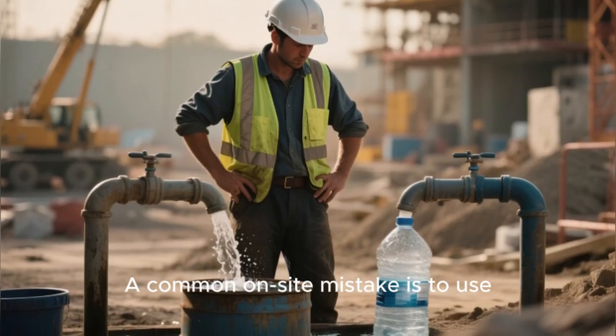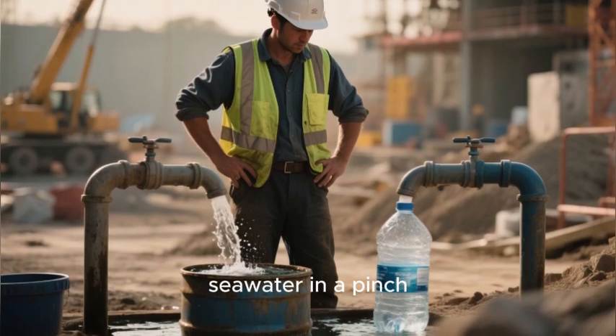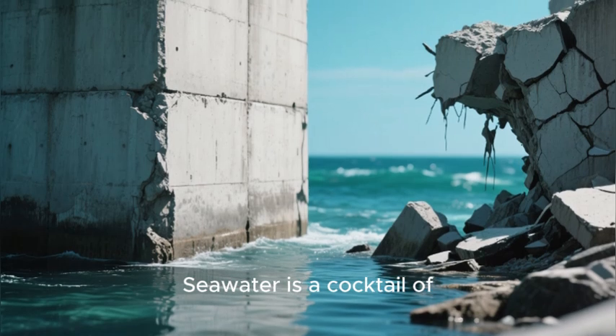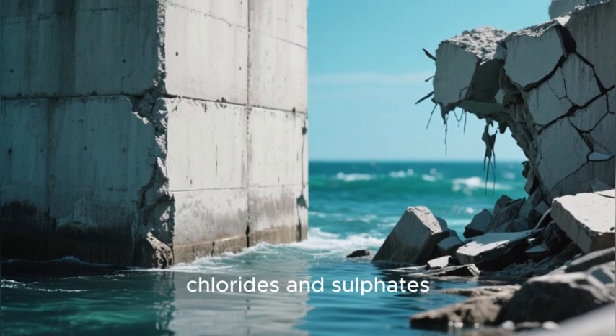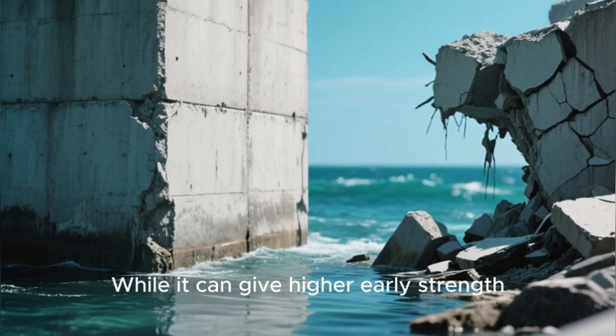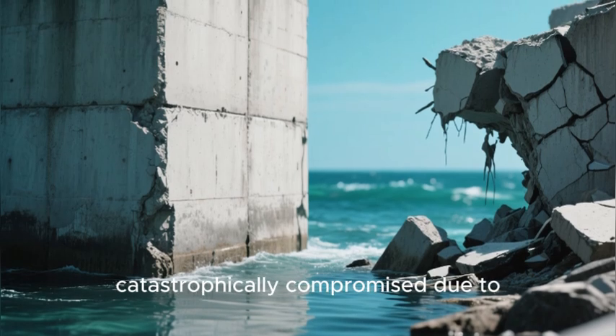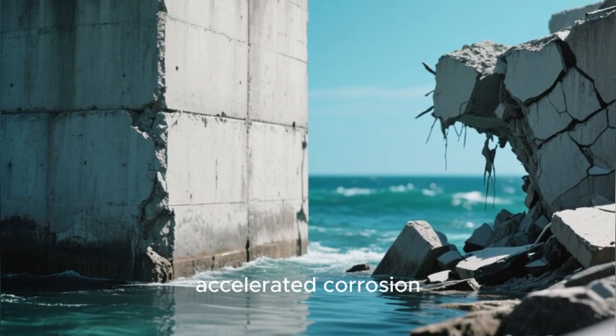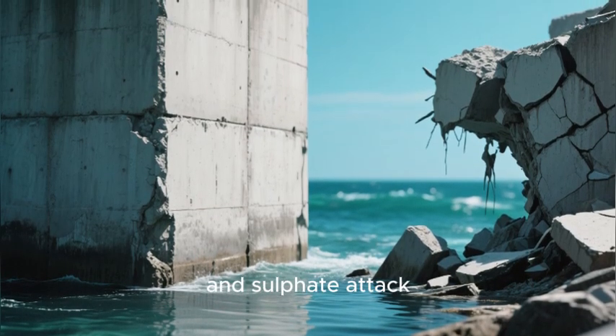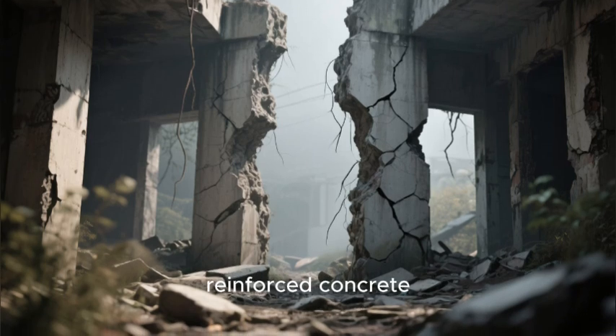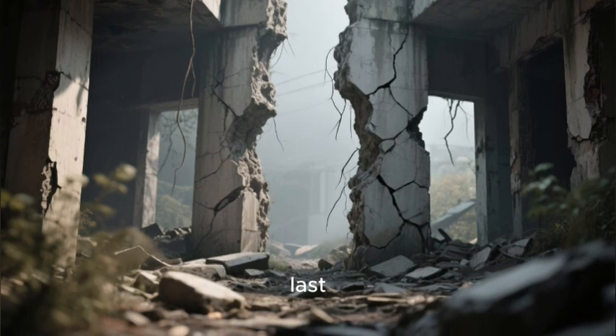A common on-site mistake is to use seawater in a pinch. Seawater is a cocktail of chlorides and sulfates. While it can give higher early strength, the long-term durability is catastrophically compromised due to accelerated corrosion and sulfate attack. It should never be used in any reinforced concrete structure meant to last.